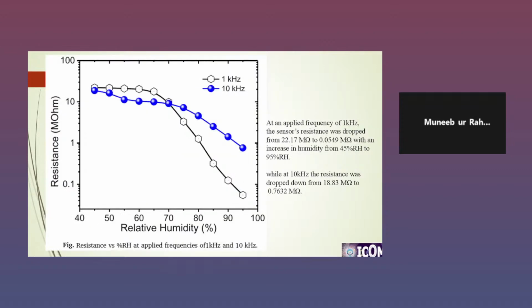This is the resistance of the device with the increase of relative humidity in percent. So we see that in both cases the resistance of the device has decreased. The reason is that in the imidazole ring, due to the N site and NH site, it interacts dualistically with the water molecule, and due to autoionization of the water molecule, it splits into OH ion and H plus ion.